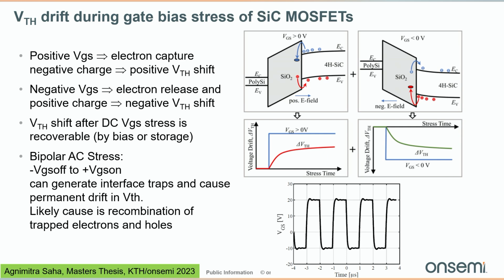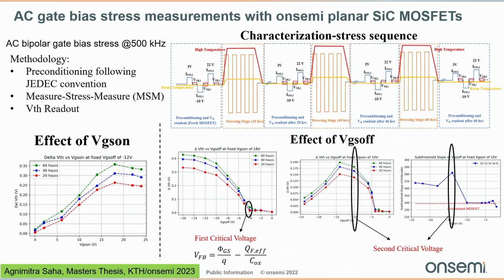And a few years ago, Infineon presented also a permanent drift due to AC gate bias stress, shifting between negative and positive VGS. That seems to cause some interface state generation and a permanent shift of VTH. And this is what Agnimitra here in the audience has investigated in his master thesis together with KTH. This is showing a little bit the measurement. We measure threshold voltage always by applying first negative VGS, positive VGS, then measuring the threshold voltage after that to have a reset and to be able to measure permanent shift.